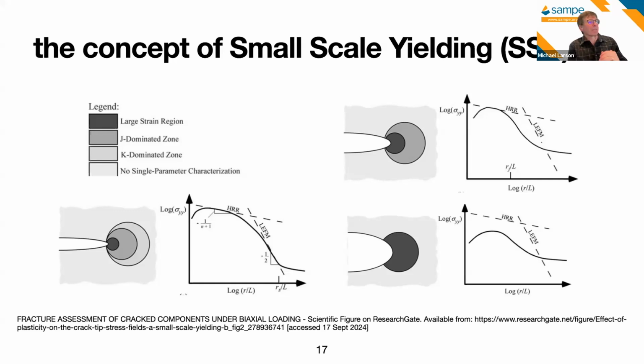And in that lower left cartoon, we see a crack with the dark large strain region, and here you can think, for a bulk material, plasticity is a great mechanism to be thinking about. It's the plastic deformation that in practice kills the stress singularity at the crack tip. So nature abhors a singularity, except maybe the Big Bang, but that's for a different lecture. Nature abhors a singularity. What gets rid of it here? It's the nonlinear plastic deformation. So there are no infinite stresses, but there is a zone outside of that where the stresses match very well that classical solution for